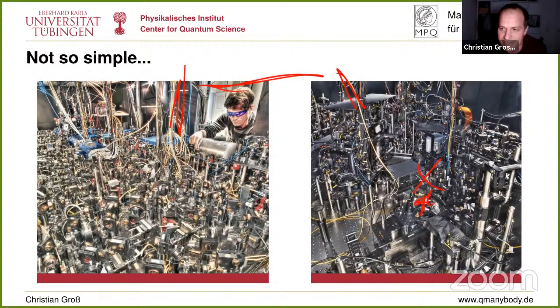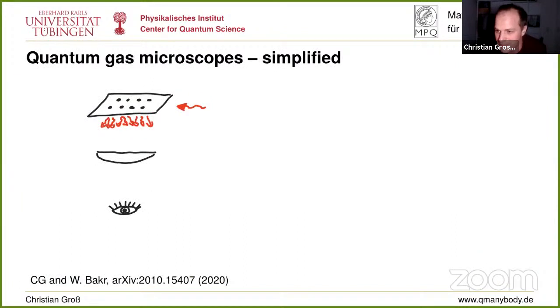So let me simplify this setup a bit for you. This is the simplified version of the setup. What this setup does is it prepares a single atomic plane in the ultra-high vacuum chamber. And then there's a high-resolution microscope from the bottom. We use specially tailored laser light to cool the atoms while they are scattering, such that they can scatter many photons, in the order of 50,000 or so, before they hop from one site to the other. Well, actually, they basically never hop. The hopping probability should be somewhat below 1%.